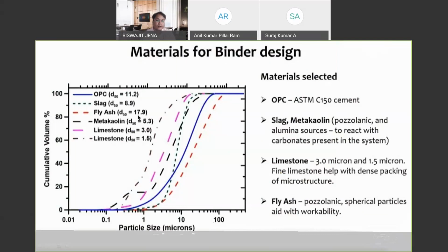But here I have not mentioned the silica fume because the size of silica fume is sub-micron. So then we use two different types of limestone powders of 3 micron and 1.5 micron size. Here we have used limestone, but you can have alumina also from metakaolin, and you can have a combination of limestone and alumina to react better. That will be a better strategy than using silica fume, even though we have used silica fume also.